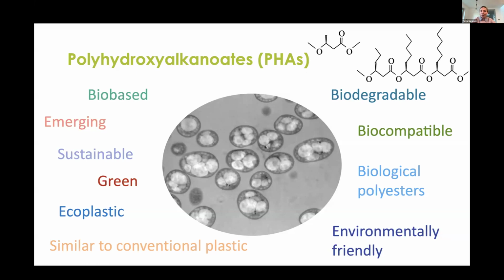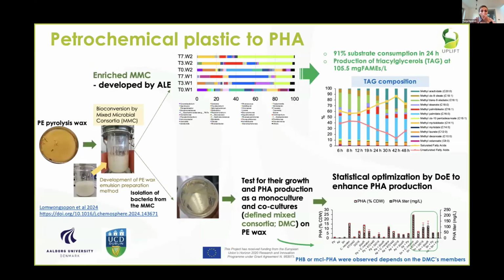So when you have short chain length PHA extracted, they look like a polyethylene bag, but unlike a polyethylene bag, if you put a little bit of stress on it, it will shear. They're brittle, they're crystalline, so they will rip easily. And for medium chain length polyhydroxyalkanoates, the longer the side chain is, the more viscous they are. And you can imagine that by combining these properties, you can have a range of different applications. And by blending these polymers, you can get interesting applications, among them packaging as well.